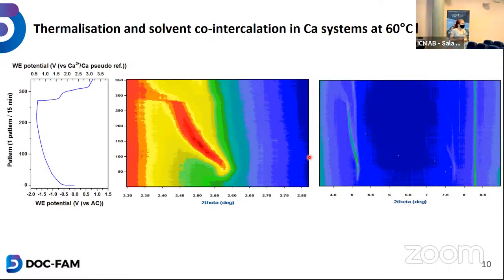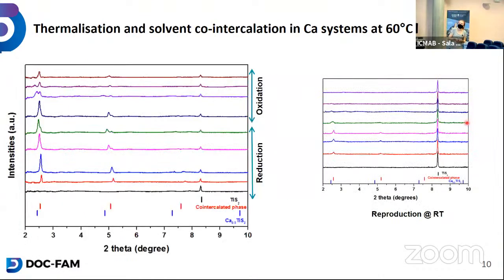So the mechanism is a bit different than lithium, because in lithium you see the peak shifting because the structural changes are not that major. When you intercalate calcium, you have to expand your lattice much more than with lithium, and so you cannot actually see the peaks moving from the starting material. So you exchange one mole of electrons and bam, you've got the peak of the calcium phase. So actually here is the co-intercalated phase, and just next to it is the calcium intercalated phase. So it means that you have inserted the calcium ion. This is what you want in a battery.